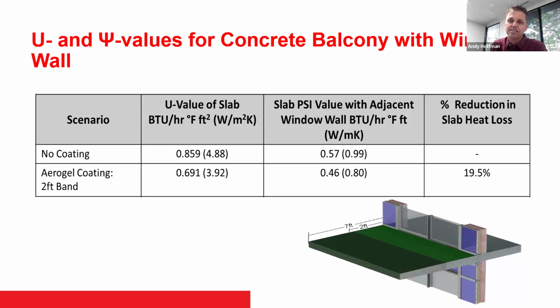And in that case, we can cut down on the heat loss through that slab by just under 20%, what you're seeing in this graphic here. There's really no difference between coating the entire balcony or just doing the 2-foot aerogel band, just so much mass in that concrete itself. Taking the coating out farther didn't really have much more of an impact. So just doing that 2-foot aerogel band, top, sides, and bottom, you can cut down the heat loss on that slab by 20%, which can be pretty significant when you think about a high rise that has all sorts of balconies sticking out.